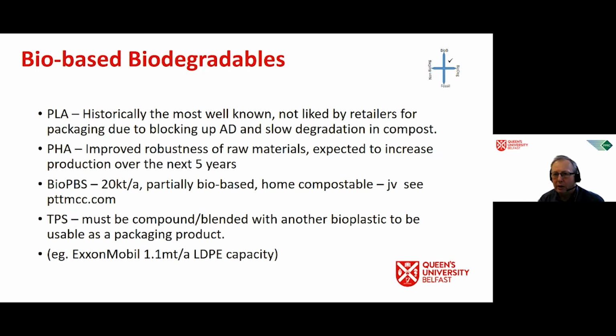So if we now look at bio-based biodegradables, the top right of the quadrant of the chart, these are materials which decompose or biodegrade in industrial composting conditions. PLA is historically the most well-known of these. However, it is not liked by many retailers or end users for packaging due to its slow degradation in composting sites. It does block up anaerobic digesters, and typically it's a very rigid film and fairly noisy on processing equipment.